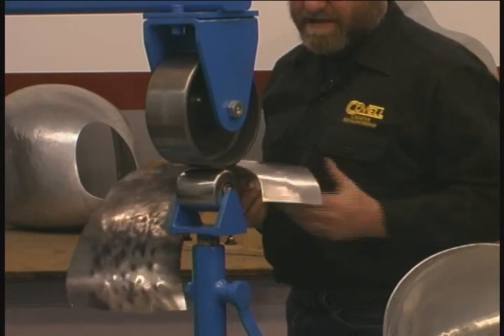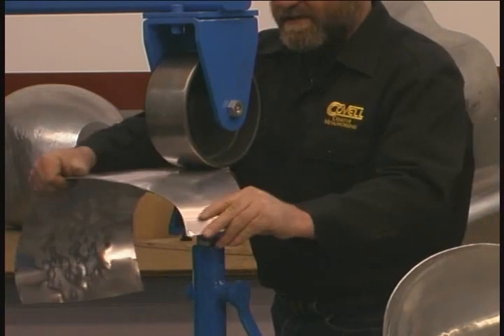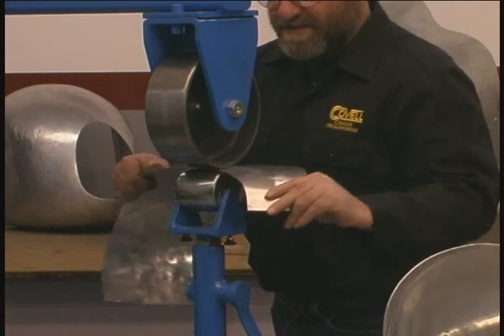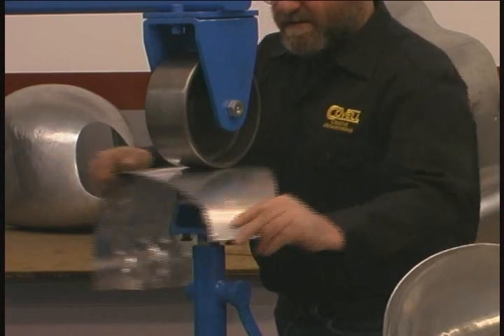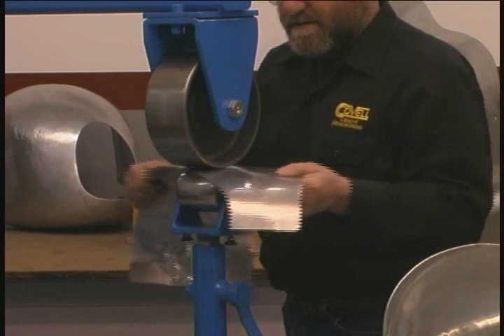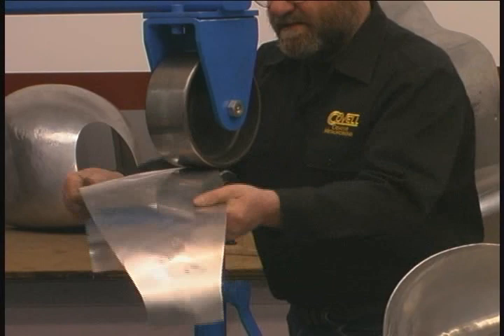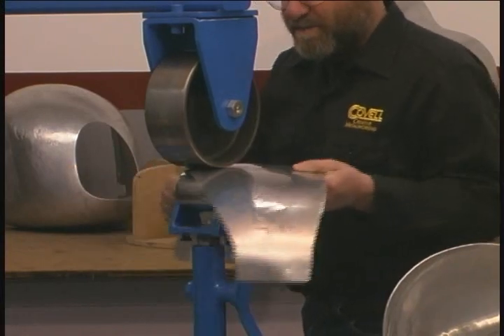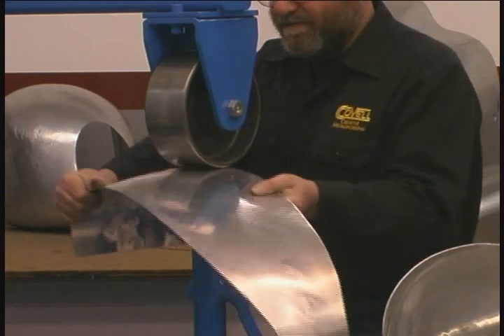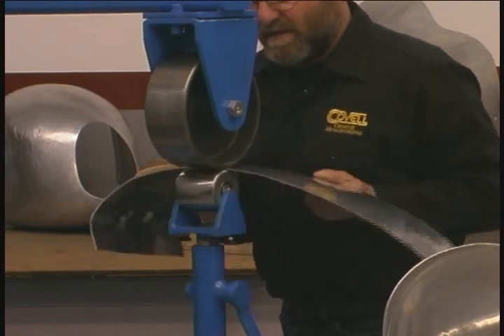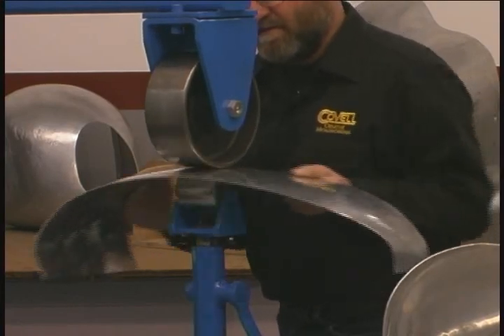So after completing one pass at 45 degrees, I'll take the part out, go across the part at the opposite diagonal angle. And now you can see the part really starting to smooth out. Even after just about 1 minute of wheeling, the major bumps have been taken out of the area that I'm wheeling over. Okay, now I'll wheel across the part straight. And this is giving us a very nice dome.